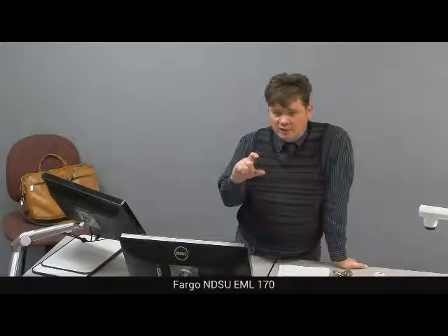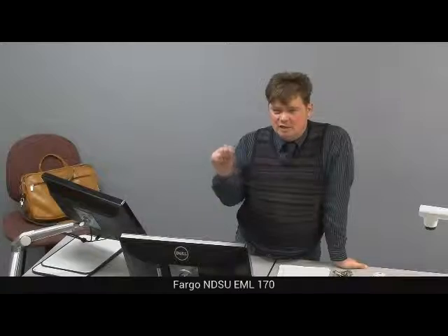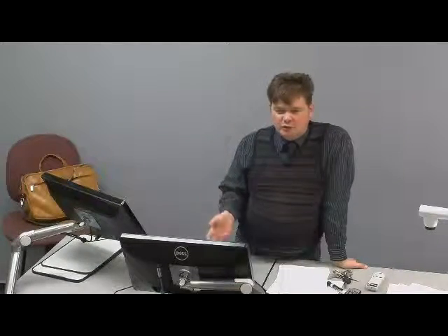So you take the template of the INCAR for molecular dynamics, and you just add one keyword, NELECT equals, and then you put the number of electrons you want. Before you start it, you need to grab the number of electrons in the neutral system. You just do grep NELECT and then OUTCAR. It will tell you like 1,000 electrons. Make sense? Yes, that makes sense.